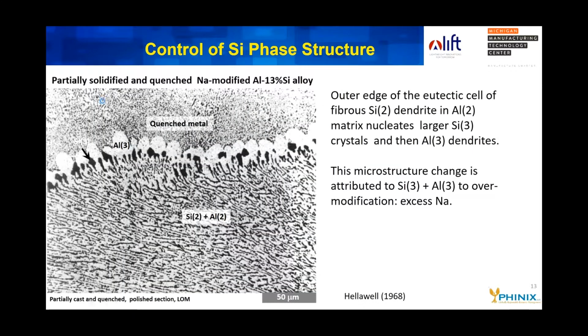Now, it is very difficult to control while water quenching, so people add modifiers to control the silicon morphology. The modifiers usually are either alkalis like sodium or potassium, or alkaline earth where strontium is most used. Those are surface active elements that modify the interfacial surface energy of melt and the silicon, and also interfere with the growth mechanisms for the silicon structures.